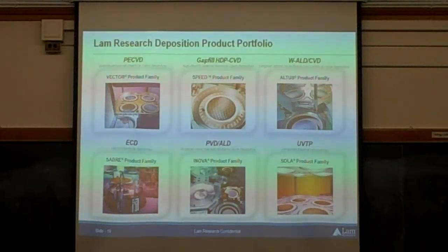And that's why it costs $5 million a pop buying one of these systems. So you can see here, this is the plasma enhanced. I didn't talk really about the super plasma enhanced, a high density plasma. So you really crank it up, and that allows you to fill certain features that standard PECVD doesn't work for. Here's that tungsten atomic layer deposition or chemical vapor deposition. This was that electrochemical deposition we showed with the copper, and here's that PVD, the physical vapor deposition as well.